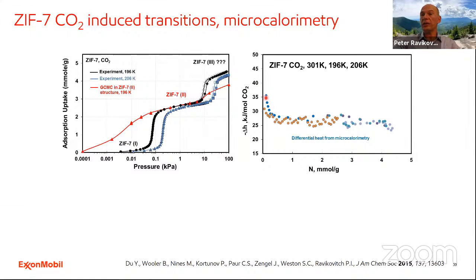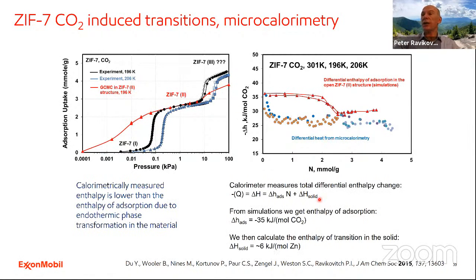And these are the measured enthalpies corresponding to the adsorption of CO2 at different temperatures. And as you can see, it's about 28 or so kilojoules per mole. However, if we overlay the enthalpies predicted from molecular simulations just for the rigid structure, there is a difference, especially in the range of this first step. And this difference is due to the enthalpy of transition. So this difference corresponds to the enthalpy difference due to the transition of ZIF from narrow to large pore phase, which is an endothermic process, which consumes some heat generated by CO2 adsorption.